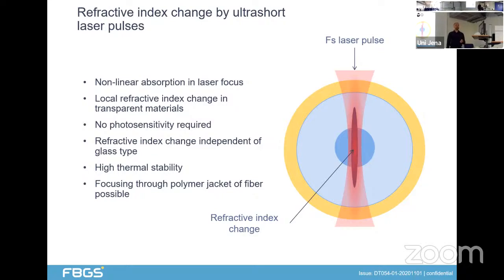Another difference to using UV techniques is that the femtosecond modifications have a much higher thermal stability. And also a good thing is if you use a laser for which the polymer jacket of the fiber is transparent, we can write through the coating of the fiber. That means with that technology, we are capable of taking any already produced fiber and writing in a second step the grating at the desired positions.